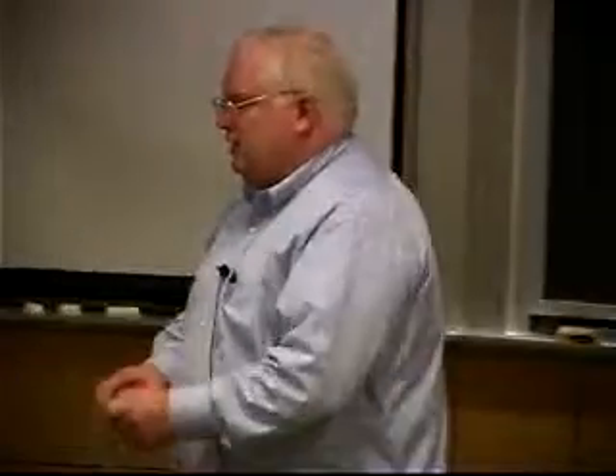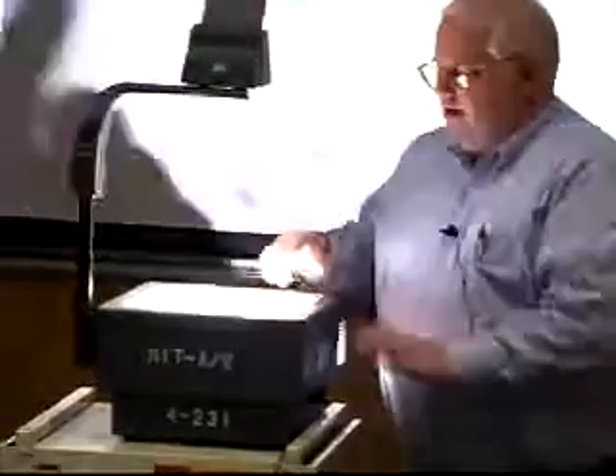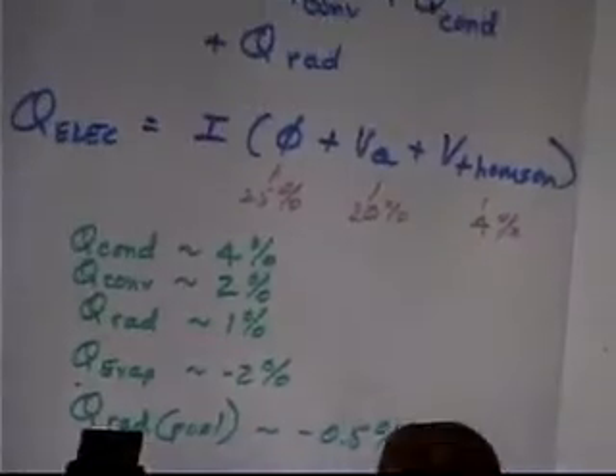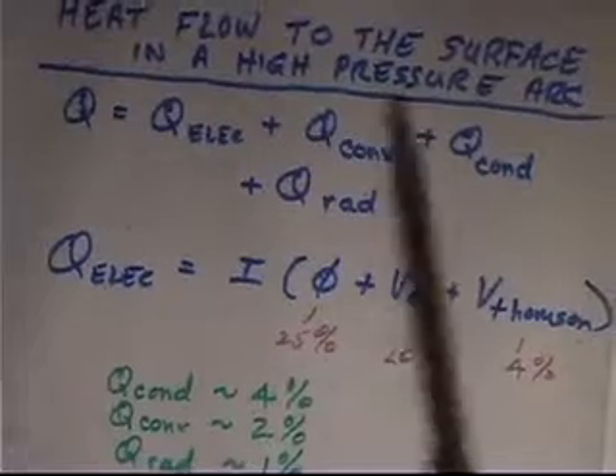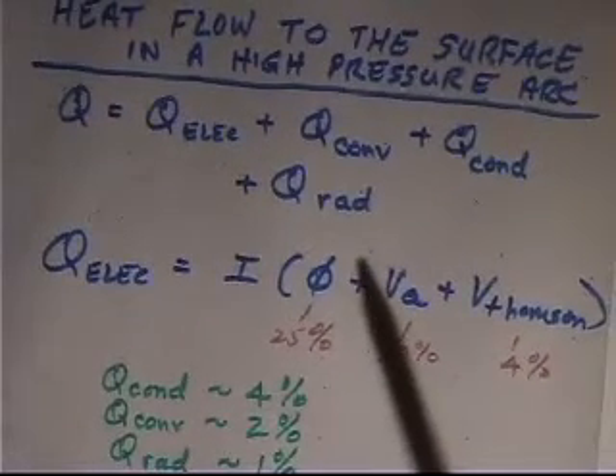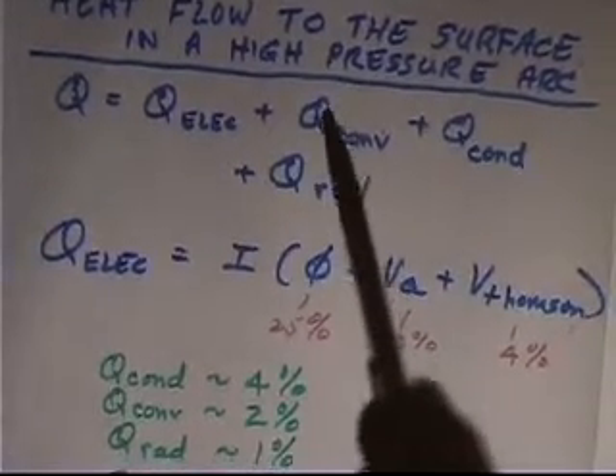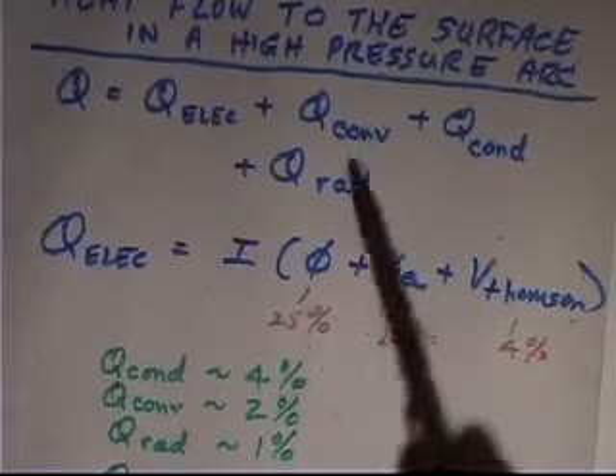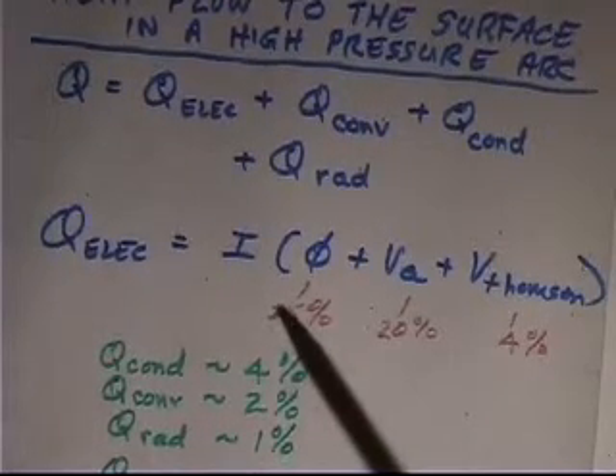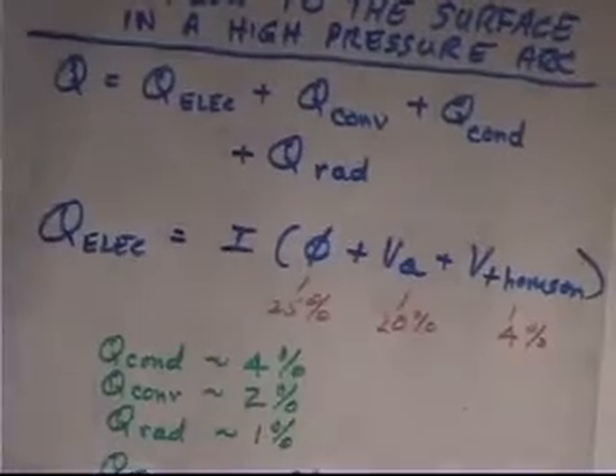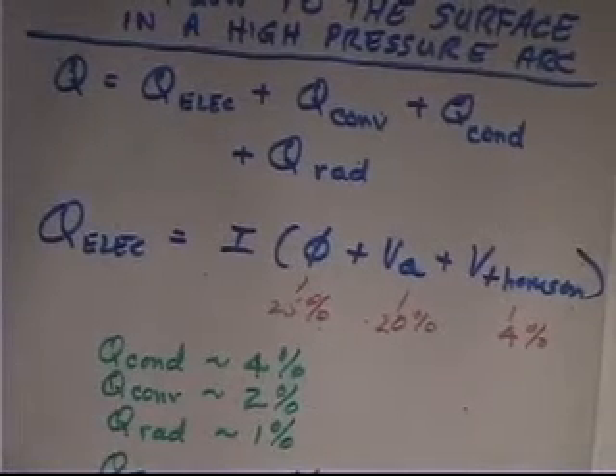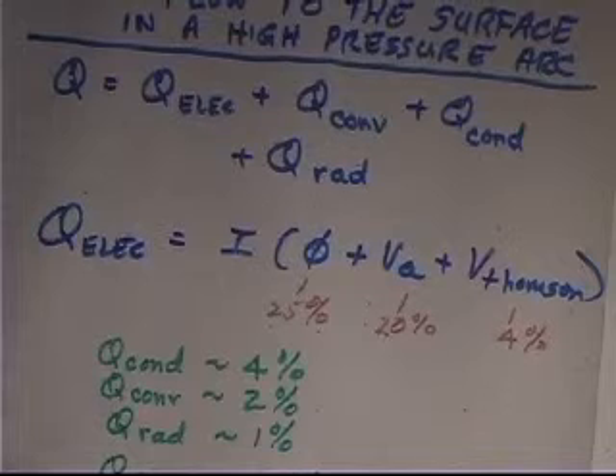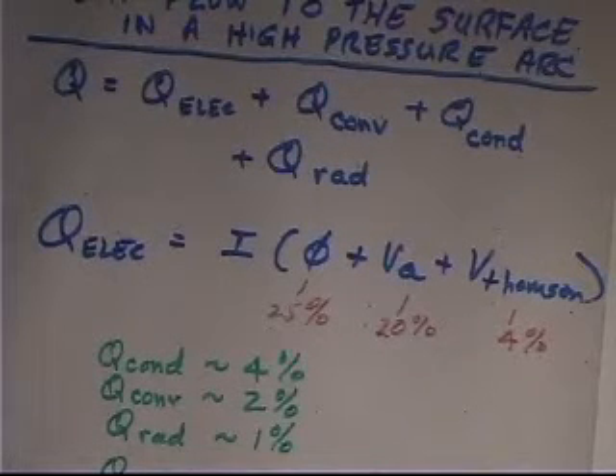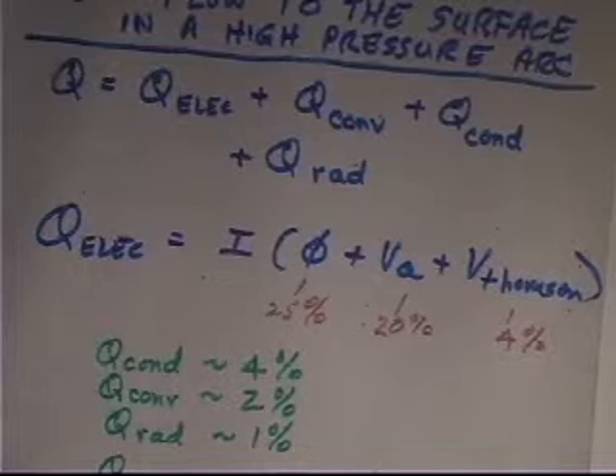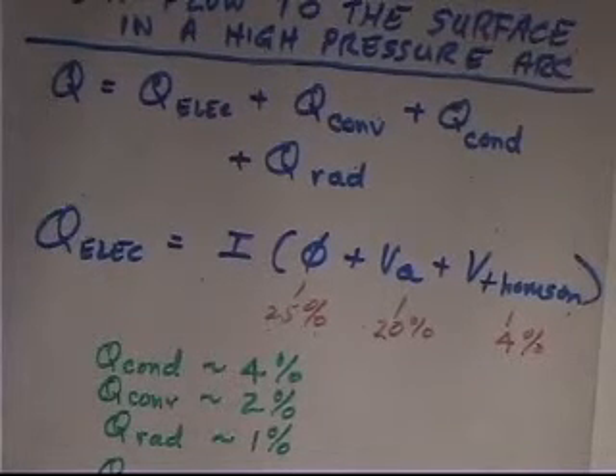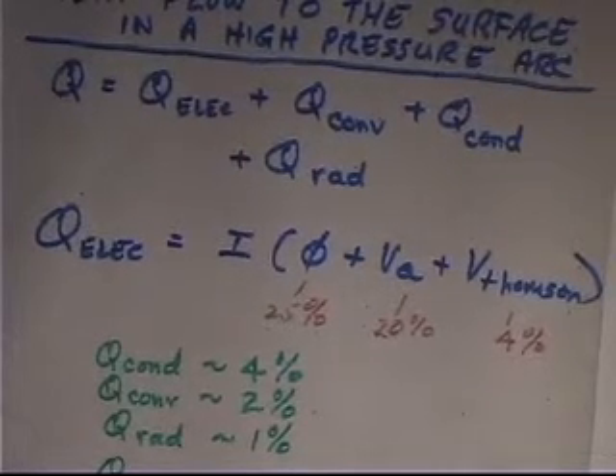So in any case, 80 to 90% of the heat is carried by the electron flow. And that's why, if I were to go back and compare, I have an oxyacetylene flame that gives me 1,000 watts per square centimeter, but I can get 10 times that by going to an electric arc where the electrons punch through the boundary layer. When I said that an arc is an electrically augmented flame, I have a high temperature gas, just like I do in a flame, but in this case, the flame is limited, remember, by its heat transfer because you can't get heat conduction through the boundary layer very efficiently. But I have electrons that punch through that boundary layer.